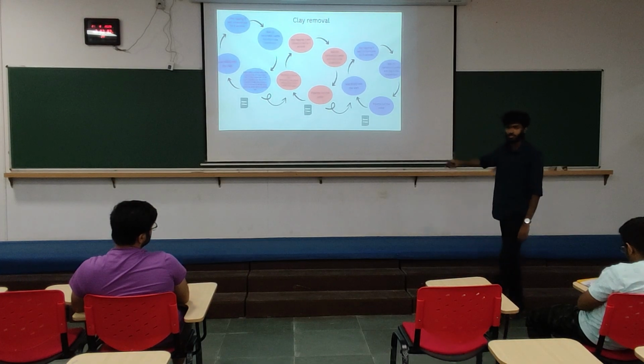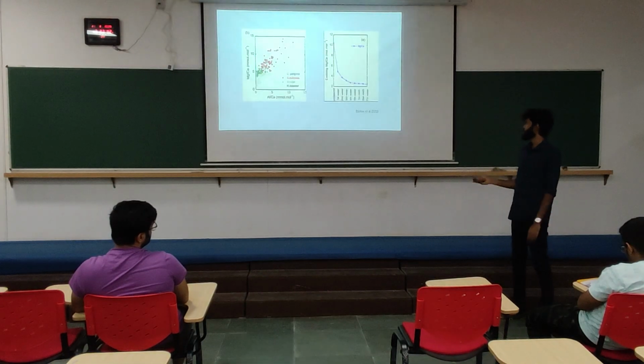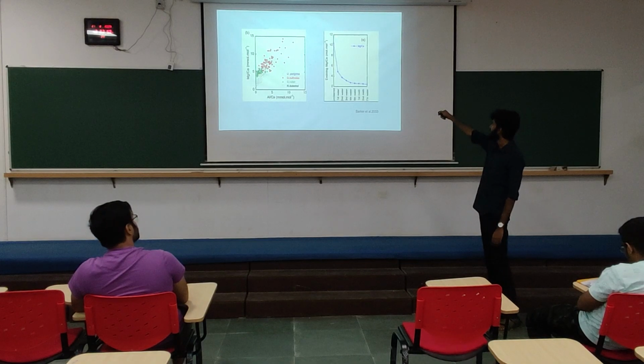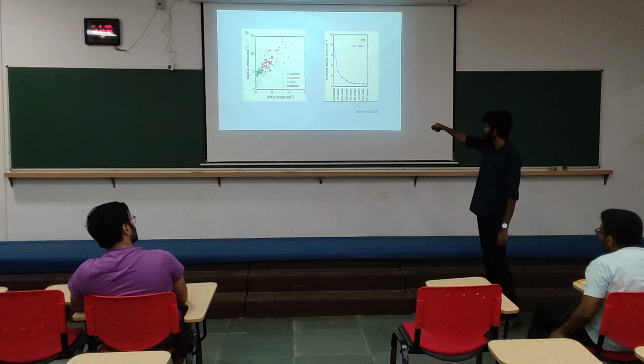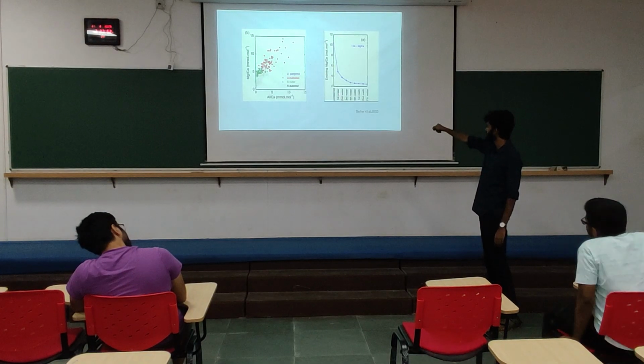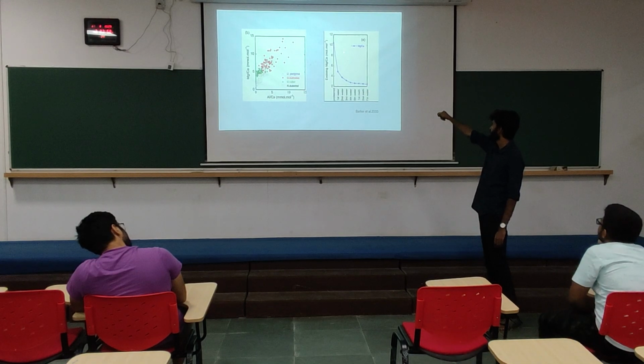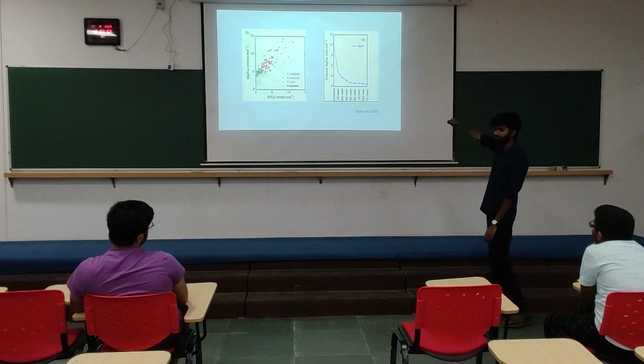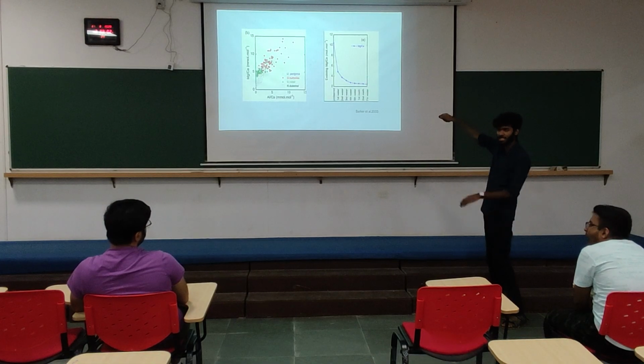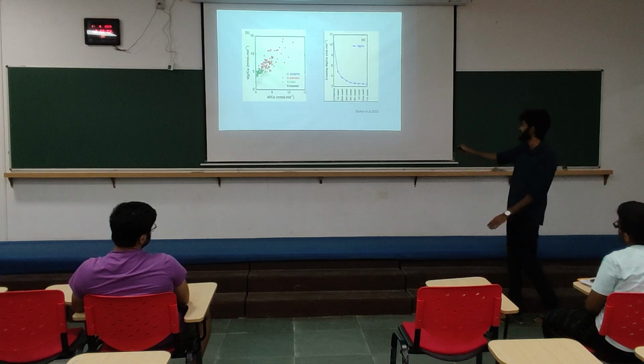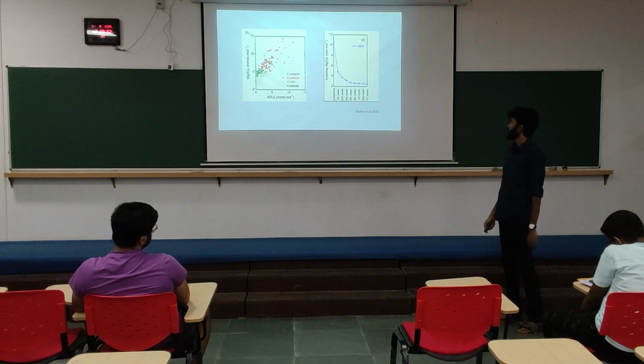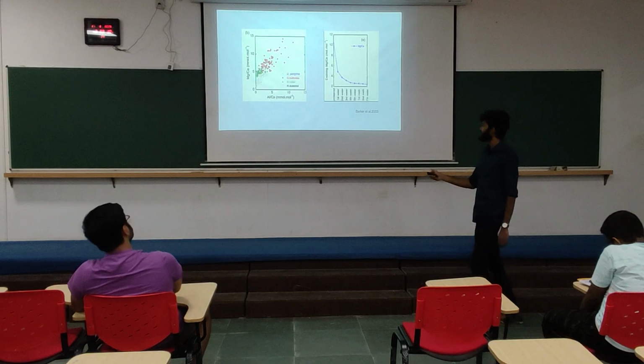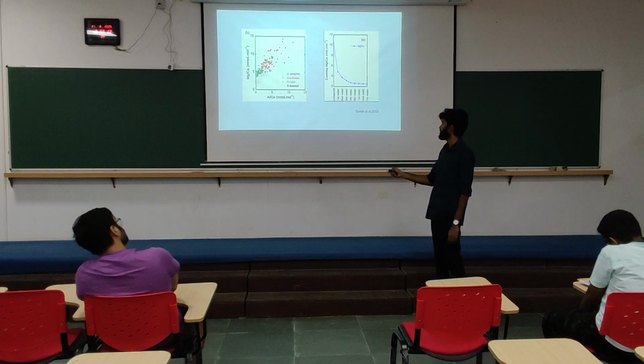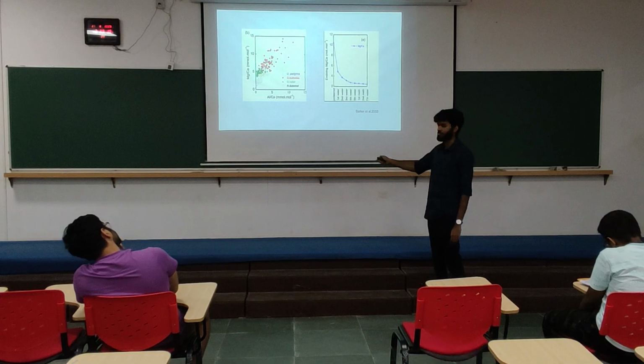At minimum, we have to do this 2 times. So that's why we are giving that much importance to clay removal. If we don't, look at this graph. We can see how the magnesium by calcium ratio was so high in the first unclean sample, and suddenly with the water steps and the methanol steps, it decreased, and then it becomes constant. When it becomes constant, that means that is the true magnesium by calcium ratio. The earlier high values were because of the contaminants. And in this graph, the x-axis is aluminium, and this is magnesium. Aluminium is the basic component of clay.